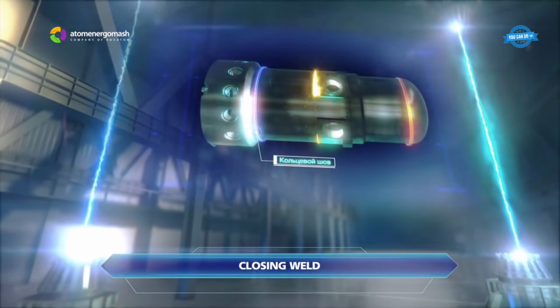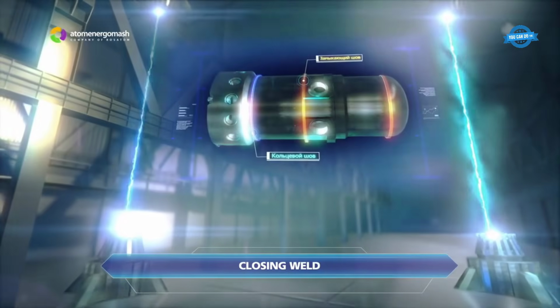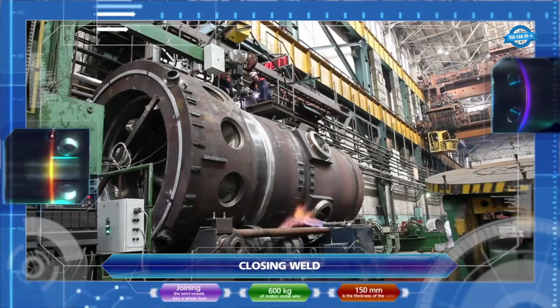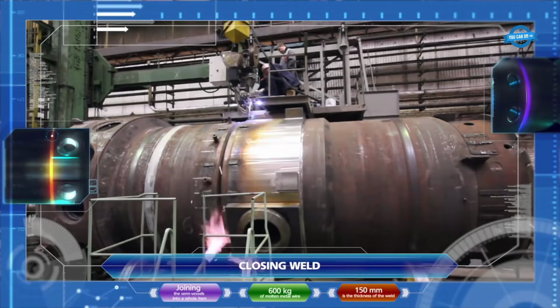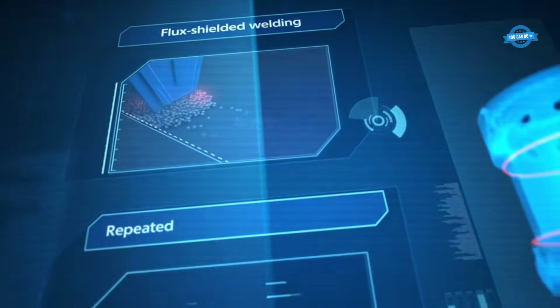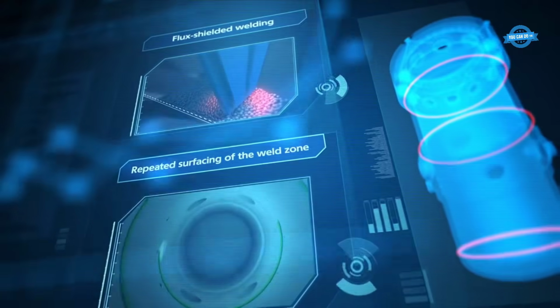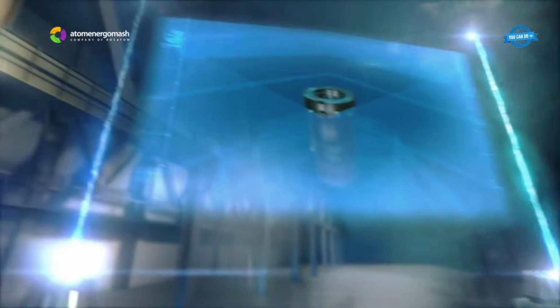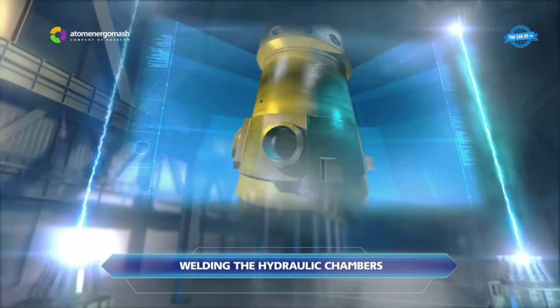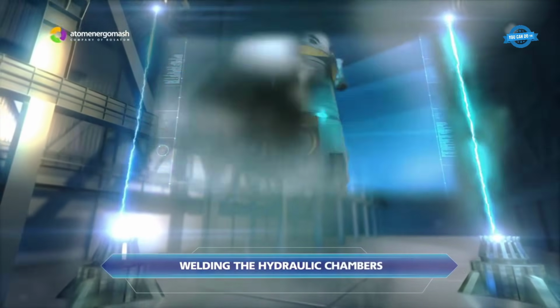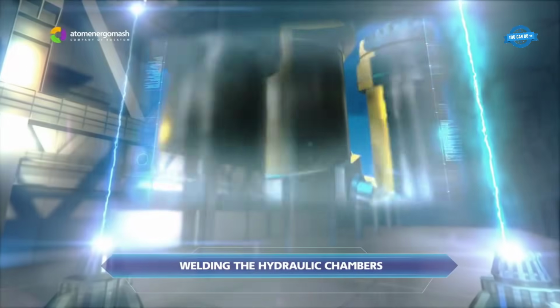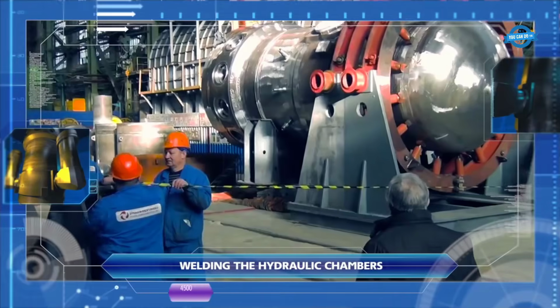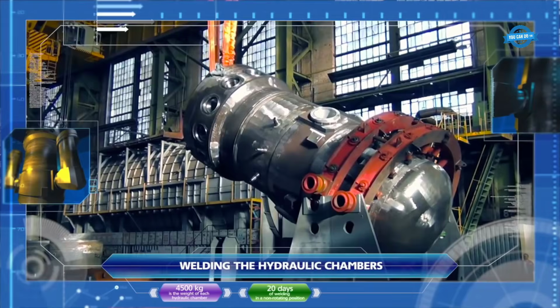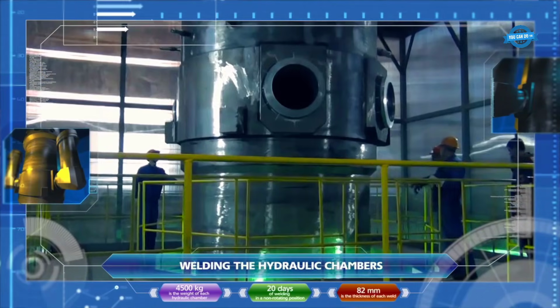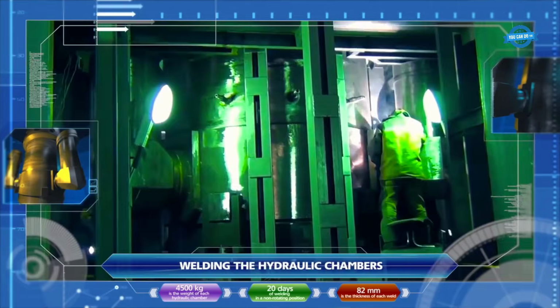Closing weld. Joining the semi-vessels into a single, cohesive unit is a critical step in assembling the reactor plant. This process requires 600 kilograms of molten metal wire and results in a weld with a thickness of 150 millimeters. Welding the hydraulic chambers. Each hydraulic chamber, with a substantial weight of 4,500 kilograms, undergoes a 20-day welding process. Welds with a thickness of 82 millimeters are meticulously crafted. These hydraulic chambers play a vital role in the operation and control of the reactor plant.